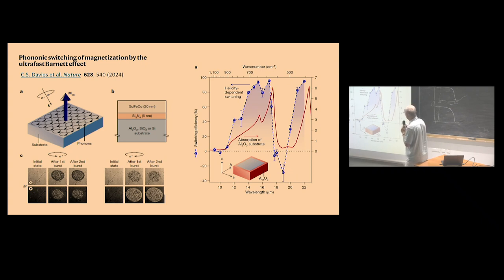And if you are close to the phonon frequency, they observed switching of magnetic domains in this ferromagnet. You can see here, without pumping, there is homogeneous ferromagnetic order, and when they pump it, they observed an opposite magnetic domain. And it can remain for a long time, of course, because you switch the magnetization. So using pumping of phonons in the substrate, you should be able to switch magnetic domains in thin films, which can finally be used in electronics.